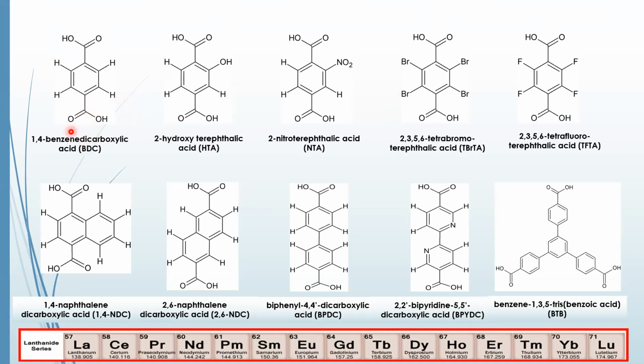If you notice, we are choosing bi- and tri-dentate ligands because these can bridge multiple lanthanide ions, leading to frameworks that have high dimensionality. And the ligands contain these carboxylate groups because these are hard Lewis base sites, and they would bind strongly to the lanthanide ions, which are hard Lewis acids. And the carboxylates have versatile coordination modes, so multiple structures can be envisaged with the same ligands.